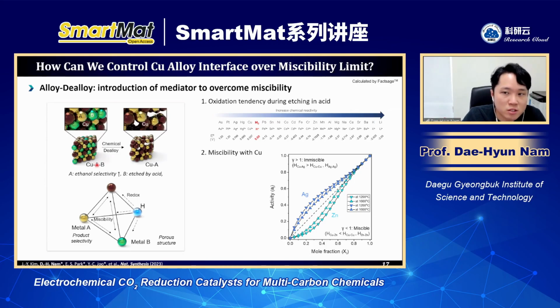The first one is oxidation tendency. When we do the dealloy process, we put this ternary phase alloy into an etchant. After dealloying, this dopant B should be selectively leached out. It means it should have a higher oxidation tendency than copper. And we also need to care about the miscibility with copper. This miscibility can be understood by the activity coefficient. This is a thermodynamic quantity, and we can get this activity coefficient by doing thermodynamic calculation.